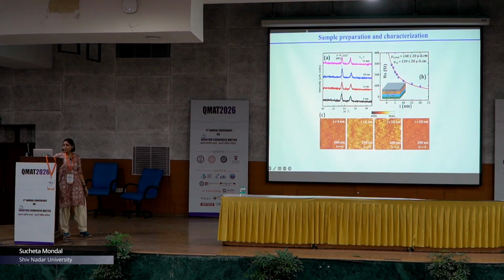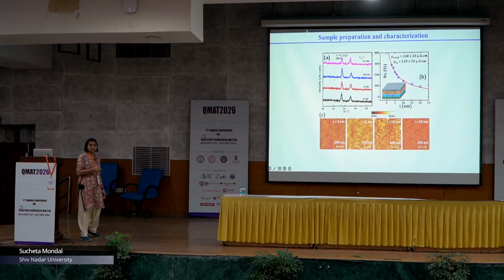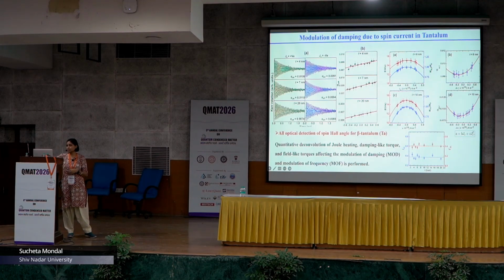So we have tried this in a system where there is no complicated phase transition. This is beta tantalum, which is deposited from 4 nanometer to about 20 nanometer, and the surface roughness is quite smooth, which also reflects that the interface might be smoother.